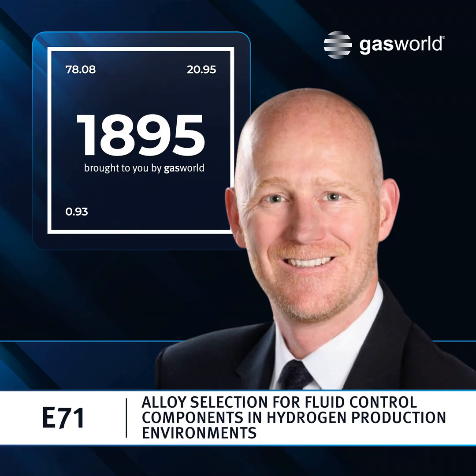So on the hydrogen side, collection includes downstream things like separators and scrubbers to remove the lye and water and to purify the hydrogen. And at this stage, the system pressures aren't really high enough to be concerned with hydrogen embrittlement or hydrogen-assisted fatigue. But you do still have a corrosive environment with more moist caustic solutions. But 316 is a highly capable alloy in those environments. In some areas, you may have higher temperatures, again, and higher caustic concentrations, and Monel can provide a good solution for that.